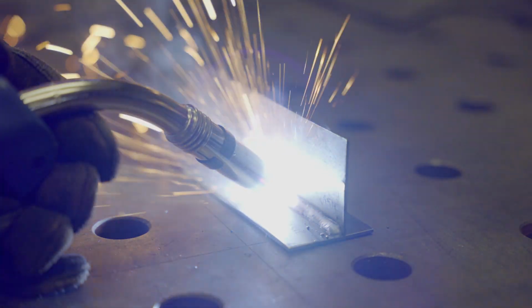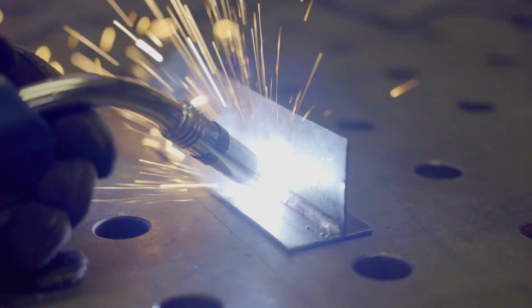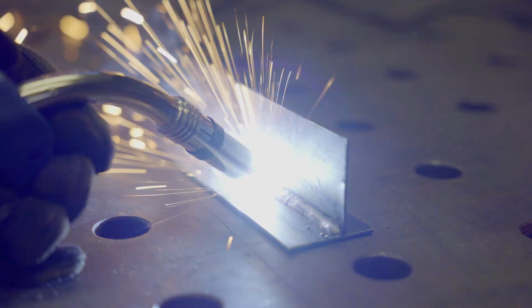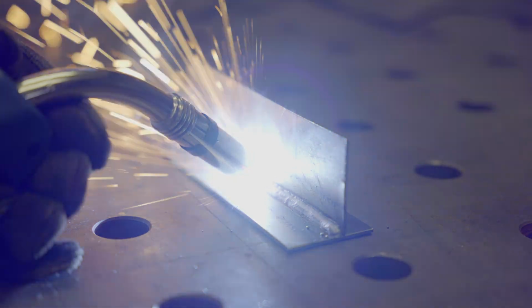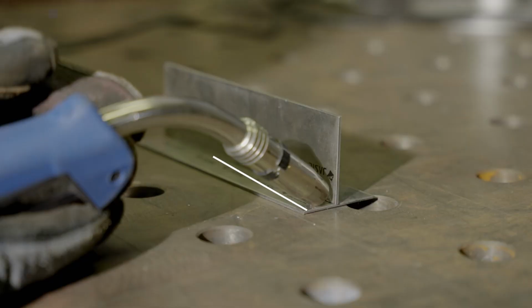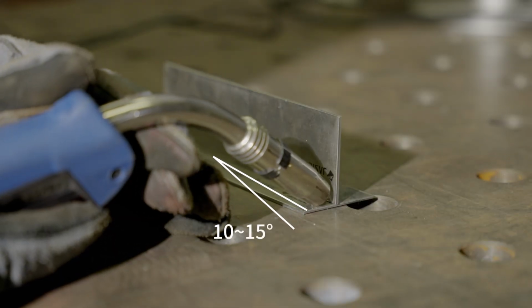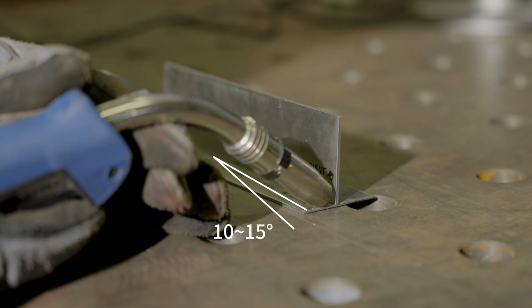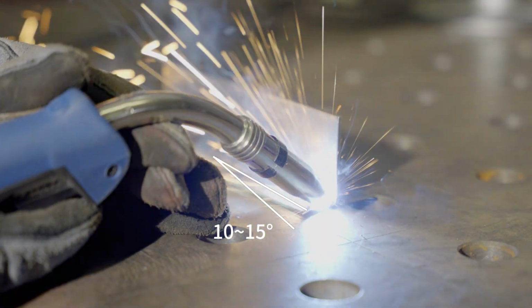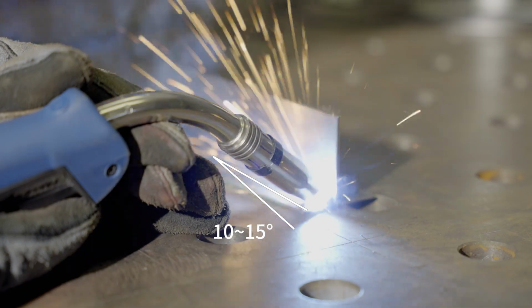When welding using a push technique, moving the gun from right to left can help reduce penetration and spread the heat more evenly across the weld. The welding gun should be angled approximately 10 to 15 degrees from vertical, pointing in the direction of travel, to focus the arc and improve control.